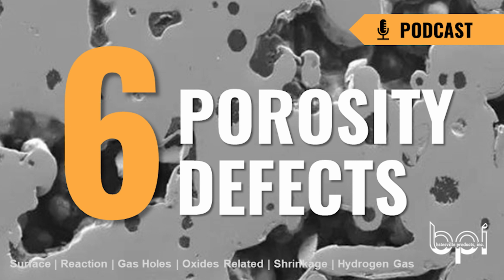Aluminum solidifies dendritically. You can get little areas trapped between those dendrites as they form, where you just haven't been quite able to get metal to them. And again, it's those interstices connected. It tends to be local. It's definitely related to feeding the part. One of the characteristics is it tends to have a very slow seep or leakage in it. One of the things that differentiates shrinkage porosity is it tends to appear elongated. Instead of having round porosity, it tends to be an elongated porosity, again because it's trapped in between those interstices, like we saw on the dendritic.